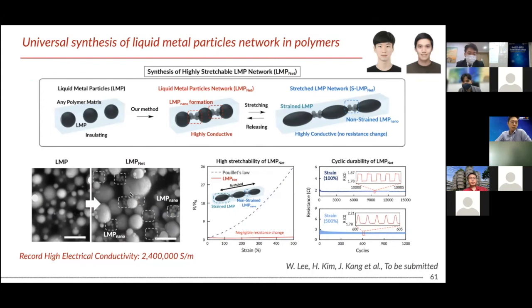But recently, we found a very interesting synthetic method. By making nanoparticles, the liquid metal particles form in between the pristine liquid metal particles and bridge them. So we call this a liquid metal particle network.